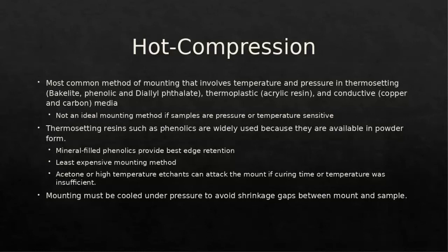So when you're looking at hot compression, this is a very common method now that's used, and I use it 99% of the time. It's a technique that utilizes temperature and pressure, and bakelite, phenolics, thermoplastics such as an acrylic resin, and you can even use conductive media. This technique is not ideal if you are working with pressure sensitive or temperature sensitive samples, just because of the temperatures that you're typically looking at when you're hot mounting, and I'll use an example of what I do regularly.